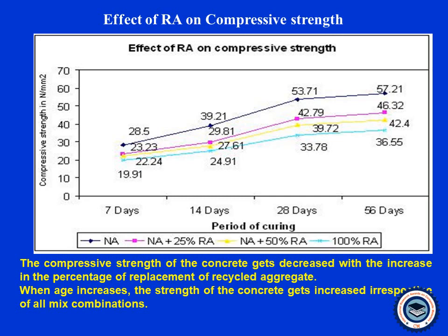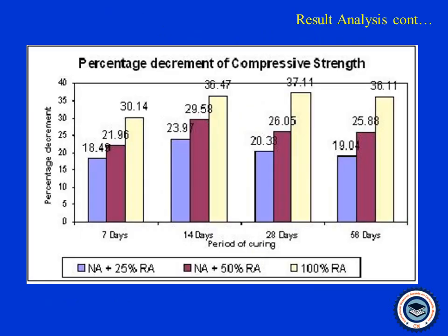So here we observed at the earlier age of 7 days it is 19.91% for 100% replacement, that is the strength reduction we obtained, and at the later ages the percentage difference is 36% for the 100% replacement, and for 25% replacement we got 19%. So the percentage decrement gets reduced when the age of the concrete increases.